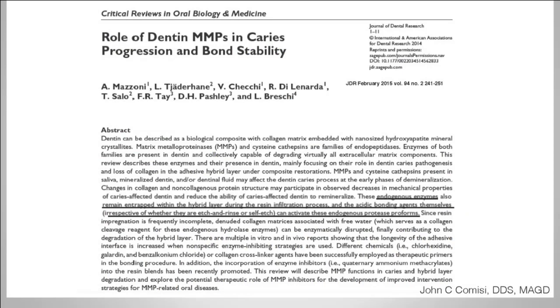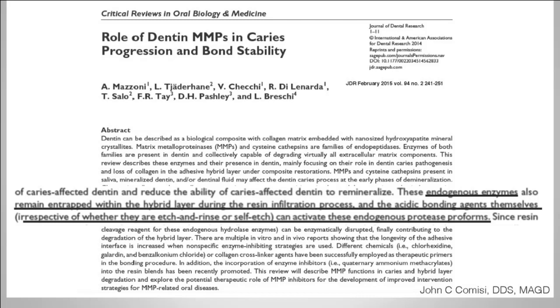In this paper by Annalisa Mazzoni and Breschi, they talk about the role of dentin matrix metalloproteinases in the caries progression and bond stability. And it's very important to understand that there's a constant enzymatic breakdown and reaction occurring because of the enzymes entrapped within the hybrid layer during the resin infiltration process. And the acidic bonding agents themselves, whether they're self-etch or total etch, activate these proteases and cause the bond degradation that you and I see, and that we seem to be finding in the NIDCR studies of 5.7-year average lifespan